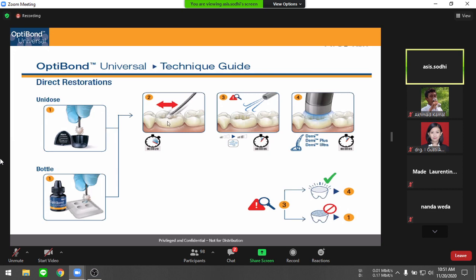Use a scrubbing motion to agitate the tooth surface for 20 seconds. Why is this important? Because as you're agitating the surface, you're also helping the acetone to evaporate. As the acetone evaporates, it increases the concentration of the monomer on the tooth surface and helps in increasing the etching efficacy, right? So it's important to do it in a scrubbing motion.